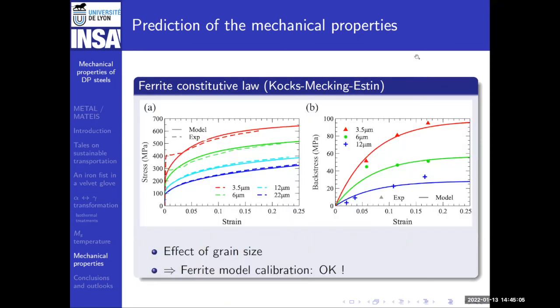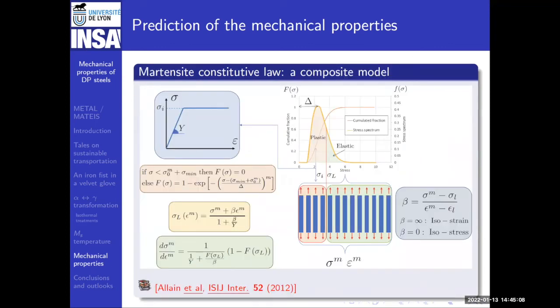Now martensite. For martensite, we use a slightly different model. In fact, the equations are too small here. We don't care about the equations. What is interesting is the basics. So we say that martensite is a mixture of many elementary units that are combined together. These elementary units have a purely elastoplastic law with yield stress that is distributed like that in this yellow function. So there is an infinity of elements with distributed yield stress. And it's kind of mimicking what is happening in reality in martensite.